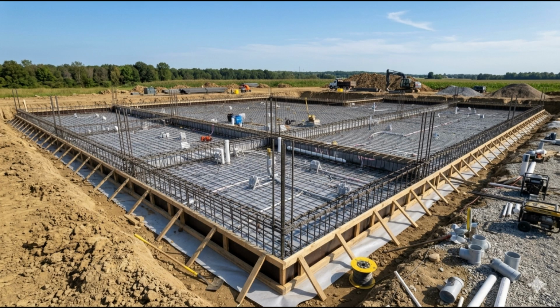This was plastic shrinkage cracking, caused by excessive evaporation from the fresh concrete surface before the surface had gained sufficient strength to resist the resulting tensile stress. The cracks were superficial and structurally insignificant, but Gerald noted them in his inspection record with an assessment of their probable cause.